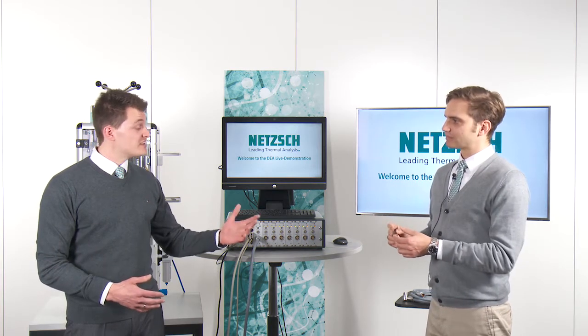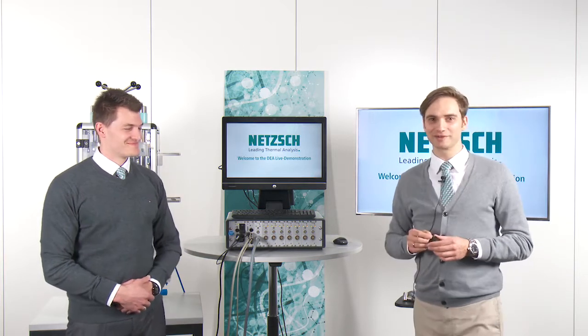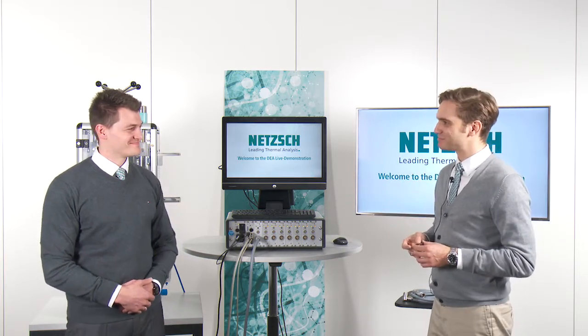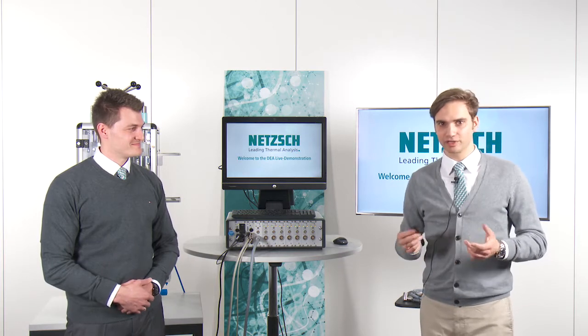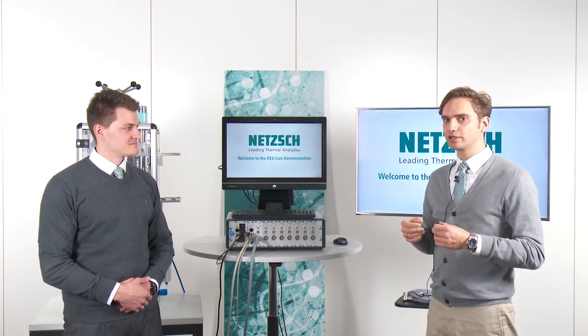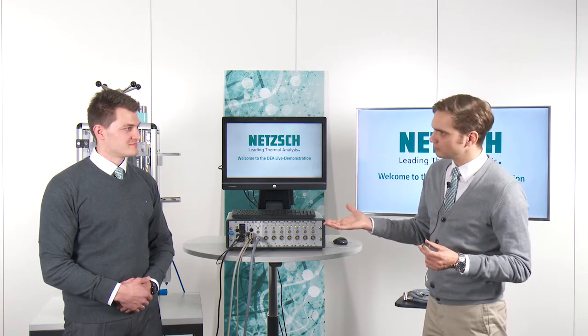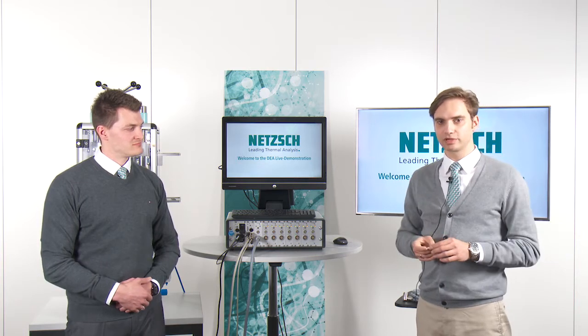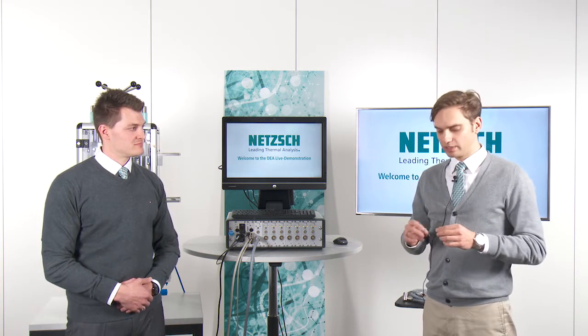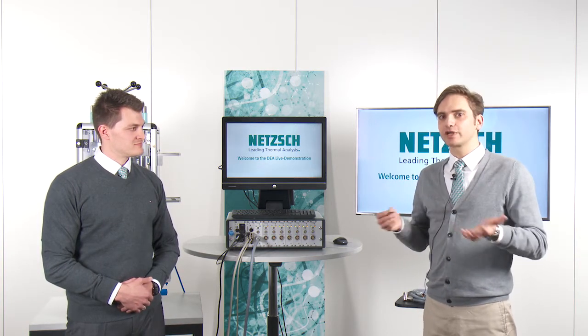Yeah, we can observe the heat enthalpy of this material during cure. Okay, so I assume Alexander knows what he's talking about, because you've done that many, many times. You can look at the curing enthalpy that comes from the exothermal reaction as the curing occurs and the cross-linking occurs inside my sample. Regularly, we would do that by DSC. Yeah. I guess that's also the method to look at exothermal enthalpy. And that is very commonly applied.